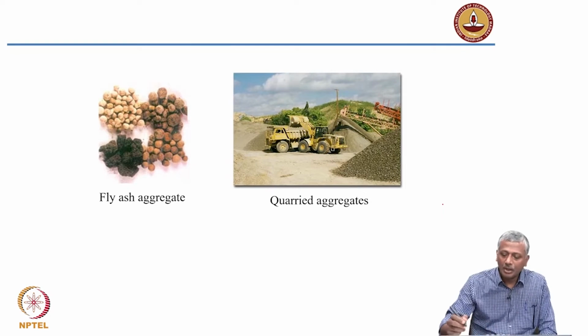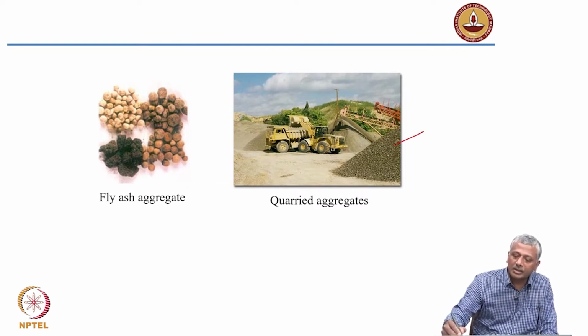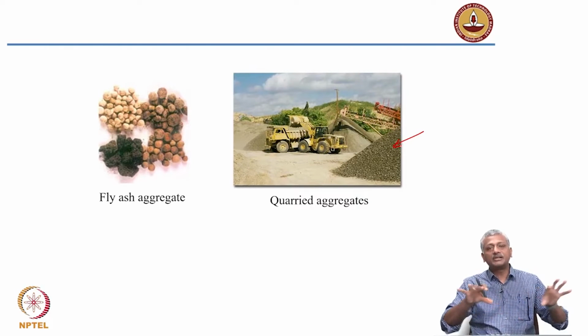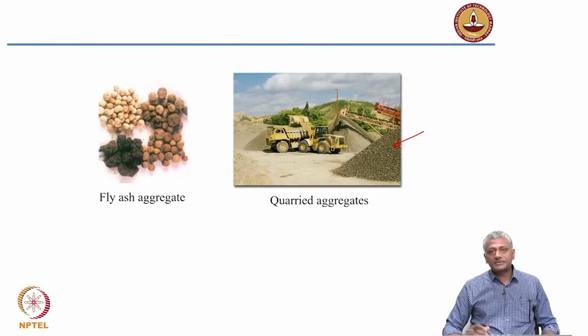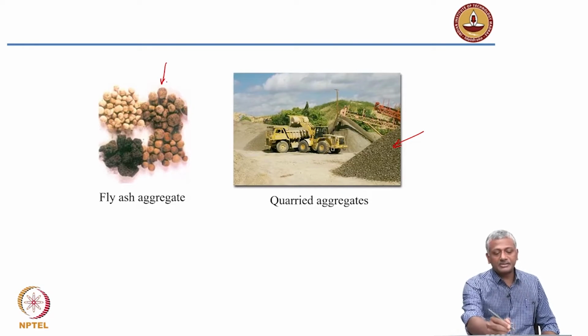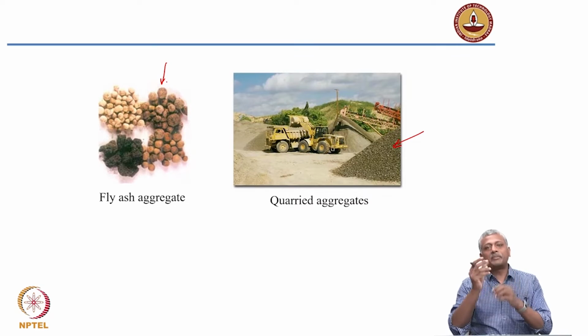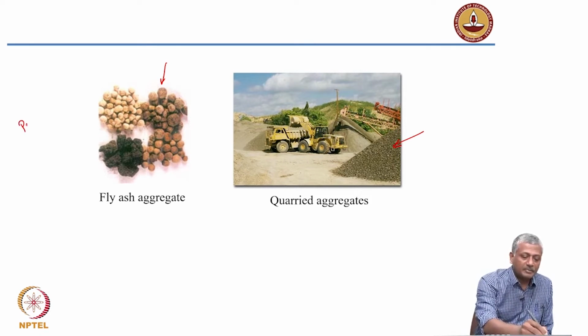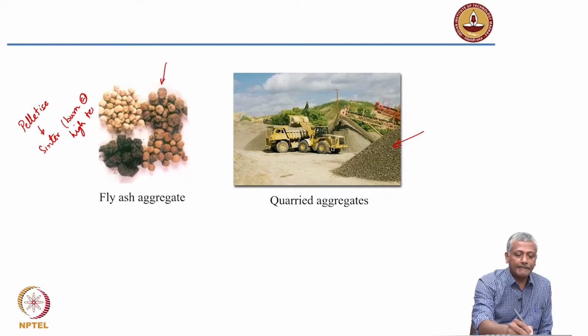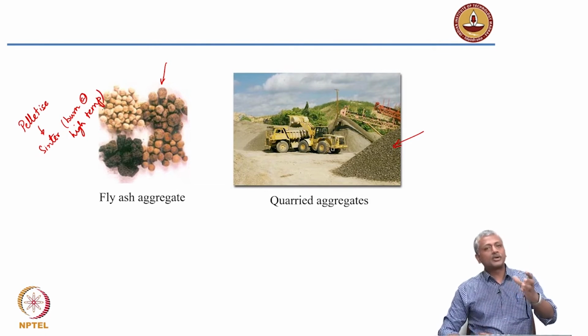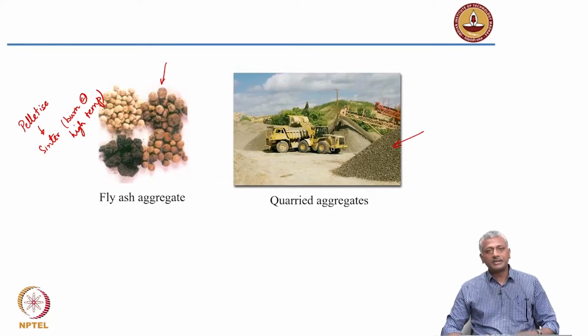So, just giving you some example of quarried aggregates. Typically from the quarry, the aggregates are broken down into smaller sizes and fractioned into different sizes, okay, and then stored as heaps. Okay. This is a fly ash based aggregate. You can see how rounded it is. That is because the particles have been made to pelletize. So, you basically have to pelletize the particles, make them into small pellets, okay, and then sinter. That means burn at high temperature. And that fuses the particles more or less like how it fuses the silica and alumina in a brick, right. Same ceramic bond formation takes place, and then you get sintered fly ash aggregate, which is a good lightweight aggregate.